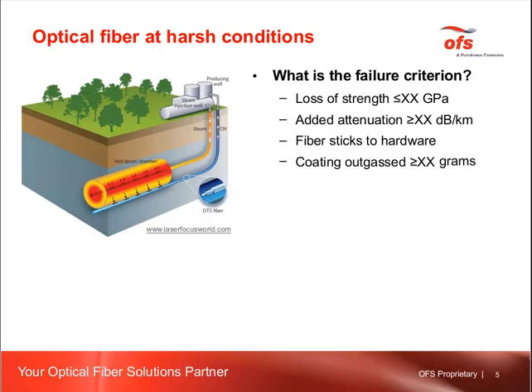Now, what can fail in the fiber and what are the failure criteria? It could be, for instance, the loss of strength by a certain amount of gigapascals. It could be added attenuation by a certain amount of dBs per kilometer. It could be something more simple. For instance, the fiber starts sticking to the hardware, or the coating is outgassing. And in any case, we should say that the failure criterion is always application driven. It depends on the application.